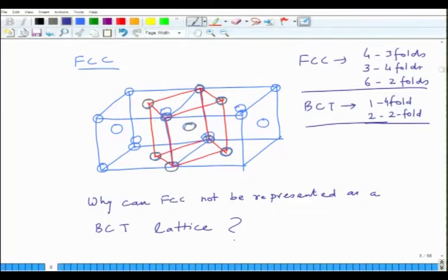So, since the symmetry of FCC is higher, we choose a higher symmetry. So, when you have this conflict of symmetry, then symmetry prevails. When the symmetry is similar, then you choose the smaller size. Okay. So, these are the two defining criteria. One is size, second is symmetry, and symmetry prevails over the size. Okay. So, this is the first criteria, and then this is the second criteria.